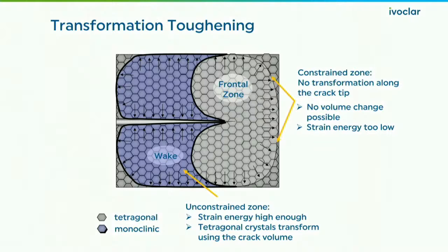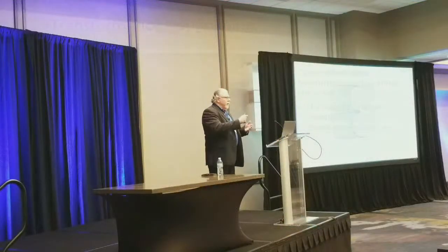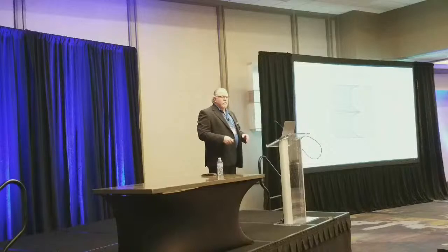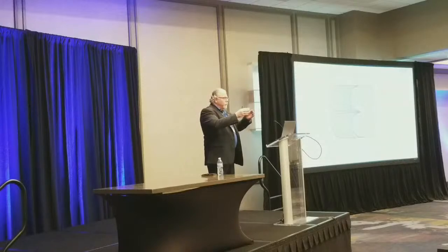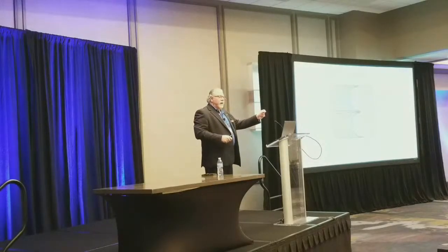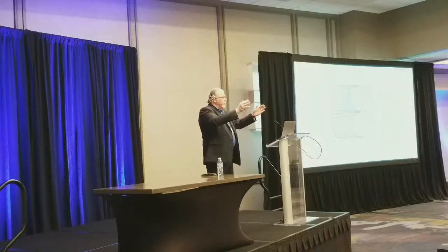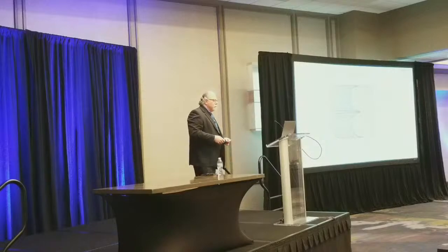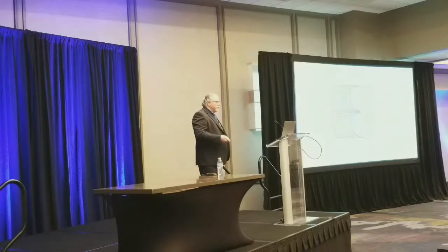So you'll see it's like a wake. The wave coming in will diminish as it hits the shore. And it's kind of what it's doing when it's hitting all that tetragonal state. It's slowing it down. And so the cracks tend to heal themselves. Now, this is important, when you go to, say, a 5Y, a high translucent material, and you treat it poorly, like sandblasting the crap out of it or grinding hot and heavy on the occlusal anatomy, you're generating that wave. And it begins that crack force. It may slow down at some point, but then when it gets to the patient's mouth, there's another force being applied which pushes the wave again, and then eventually it cracks and it's weaker. So there's certain things that we as technicians do to zirconia that we need to minimize this wave.